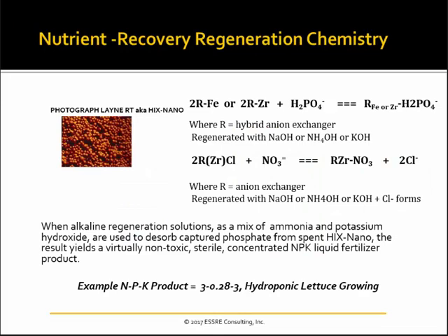So it's a ligand. It's not exactly ion exchange chemistry. So the nano iron oxide is associated with the resin. It'll actually bond, or you have the physiochemical bonding of a phosphate ion onto the resin, and you release the phosphorus, go the other way, by regenerating with weak alkaline solution, caustic soda. But sodium doesn't add any nutrient value, so I'm proposing regenerate with ammonium hydroxide or potassium hydroxide, or a combination of both. So I mentioned nitrate too.